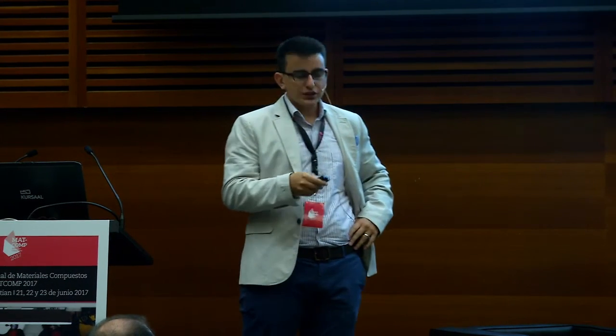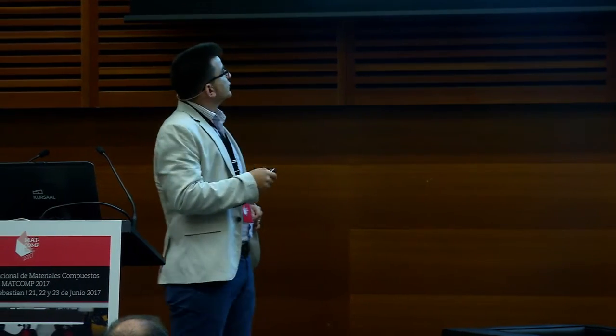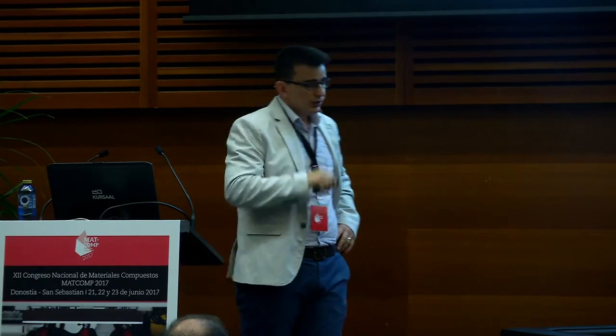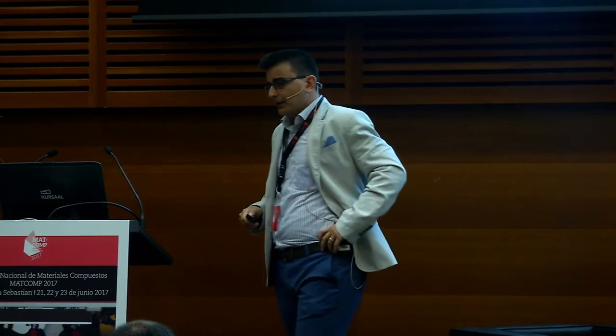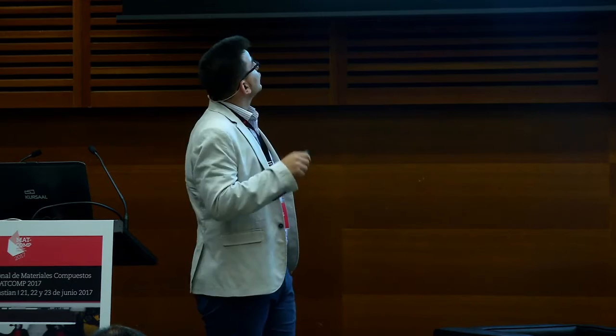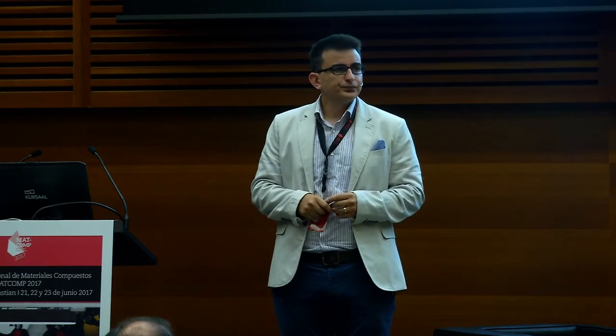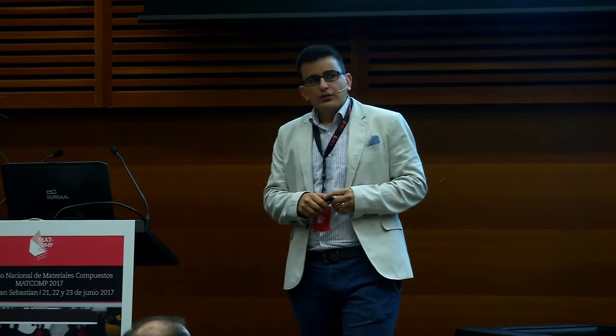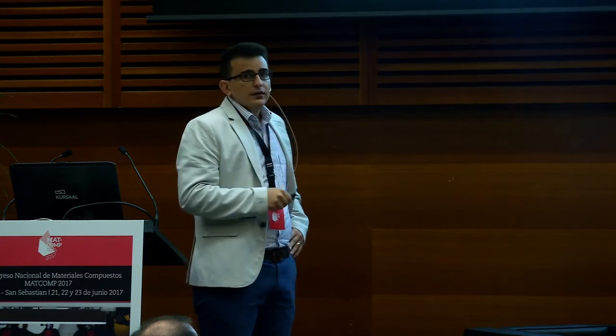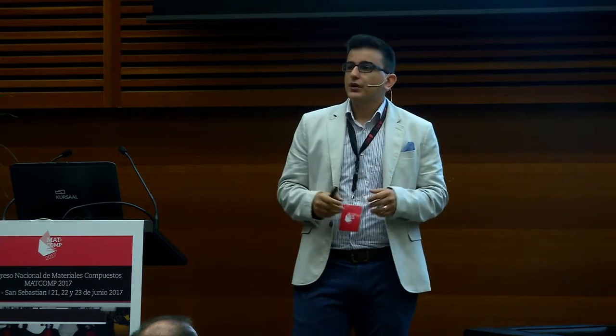Okay, let's investigate what would happen in the region of interest with the local mesh. Recall that we have the local mesh here. This is the uniform stress distribution, and we are concentrating on this local region of interest. We have one result from the uniform fiber volume content, and it's obvious that all stress components are negative, so we have only compressive stresses in this region. With the local mesh, the stress field, as expected, changes significantly in terms of magnitude and sign. Now we have tensile stresses in the pure matrix region.